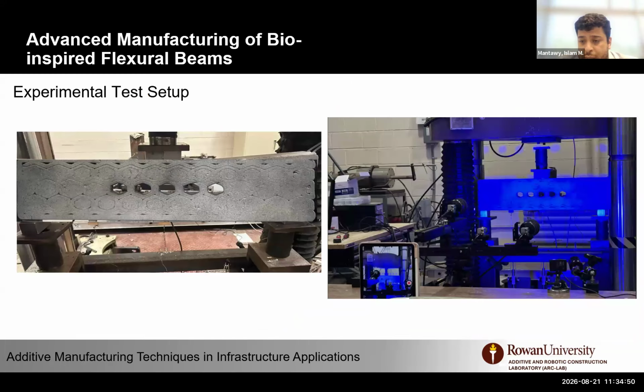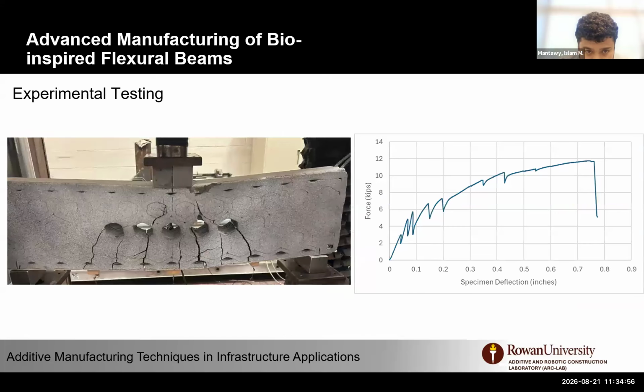So for one cable, in this cable reinforcement, we took this and we tested, and you can see the DIC system here. What we noticed from this cable reinforcement is that, because of the slips that happen to the cable, every time you have a crack formation, you will have a slip of the cable, and after that, you will have the re-engagement. So every peak you see on this curve is representative of the initiation of a new crack.